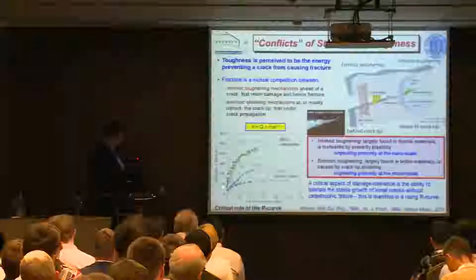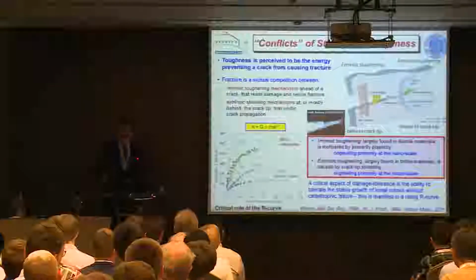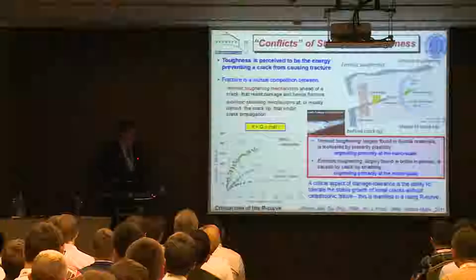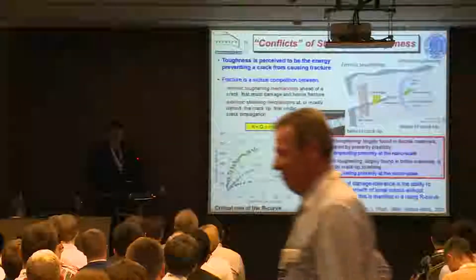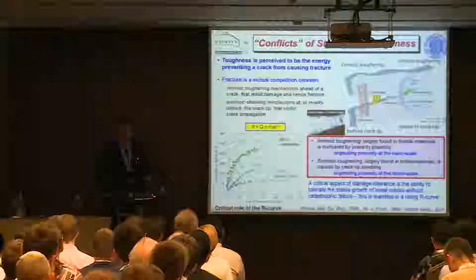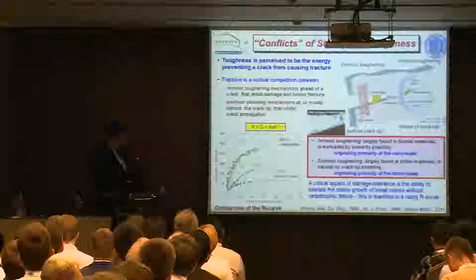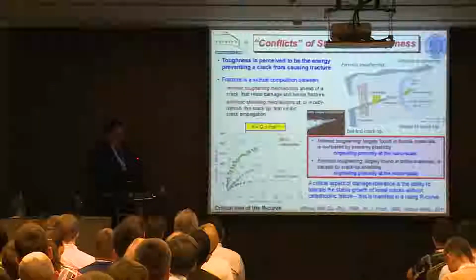We've heard about that the last few days. This is sort of a toughness parameter as a function of crack growth. And the R curve is absolutely fundamental, in my opinion, from the perspective of damage tolerance. You don't want things to simply break catastrophically. You want them to be able to tolerate damage, and damage means slow crack growth in many cases. So the generation of an R curve is extremely important.